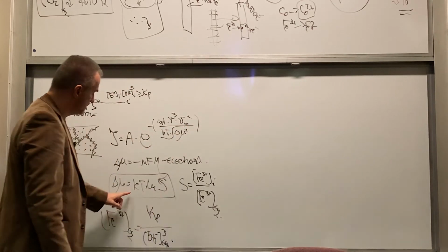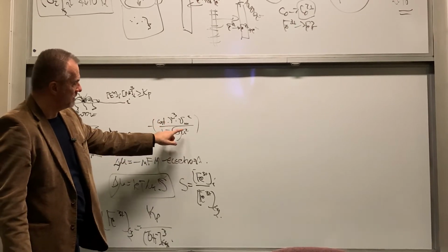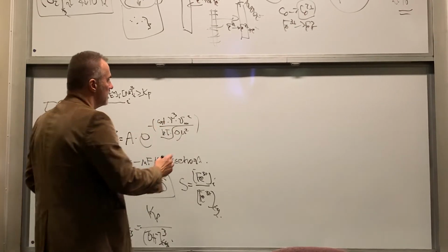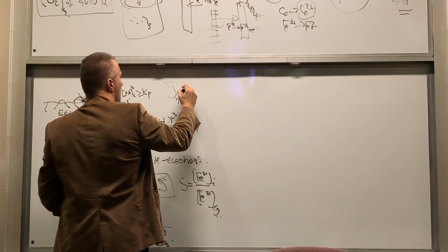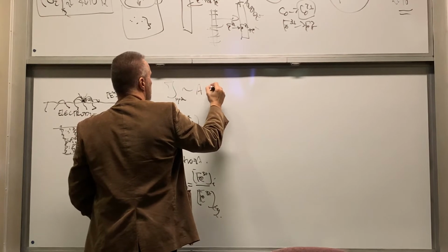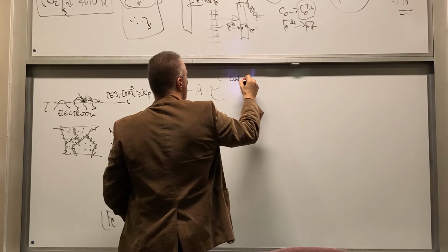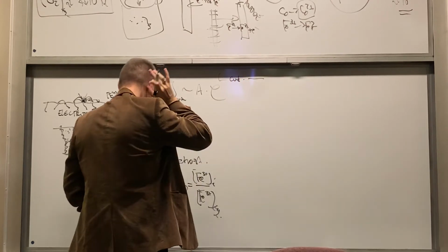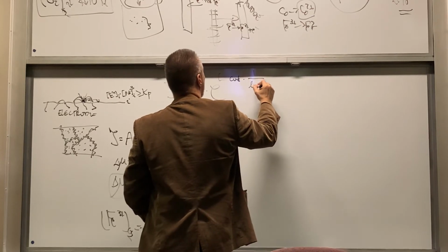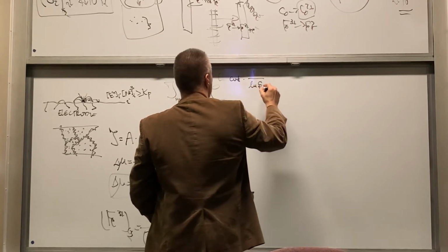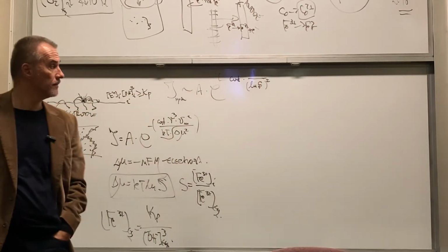Well, actually, if I put this kT ln S instead of this, it's going to be kT to the power 3, and then it's just going to be ln S. So we can say that nucleation of our hydroxide is proportional to some constant times e to the minus, a constant multiplying 1 over ln S to the power 2, right?